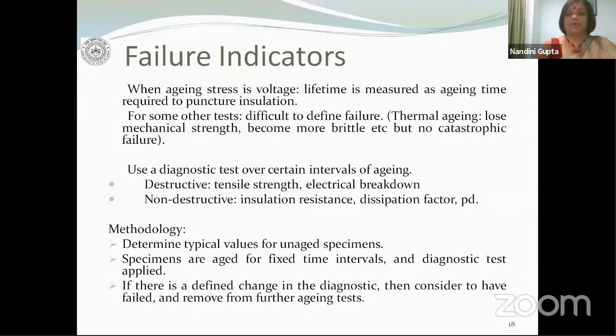But for other tests, it may be difficult to define failure. For example, even if actual dielectric failure does not happen, the material might be rendered unsuitable for use. And at any point of time, after a certain age, the material is better to be taken out of service, or you would face unexpected outcomes. So therefore, in that case, you would have to look at certain diagnostic tests. For example, if you're looking at thermal aging, what might happen is the dielectric may not break down, but the material becomes brittle. So even though it does not break down dielectrically, you cannot handle the material because the material crumbles. You do not want your insulation to crumble and just go away.